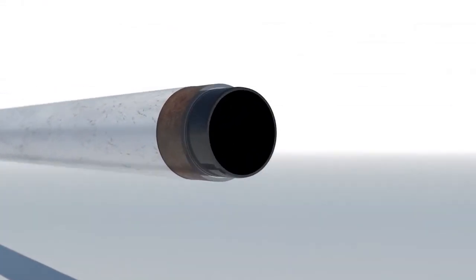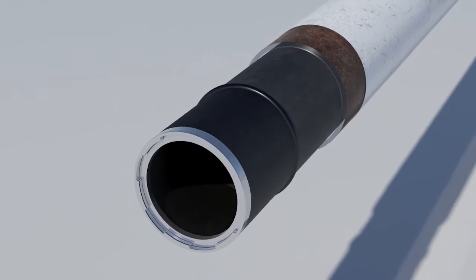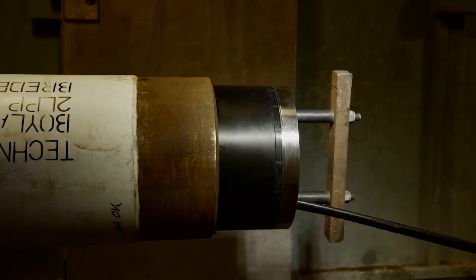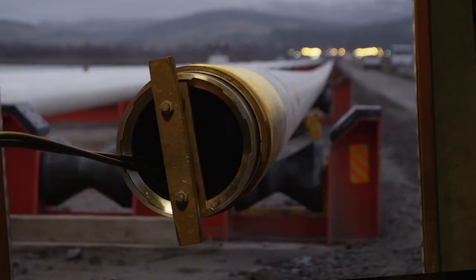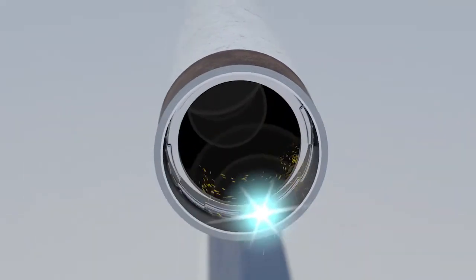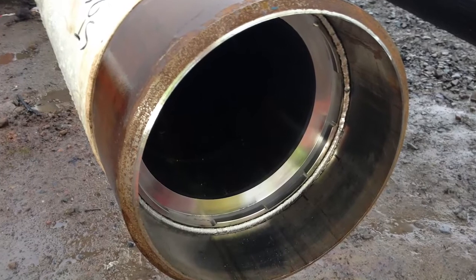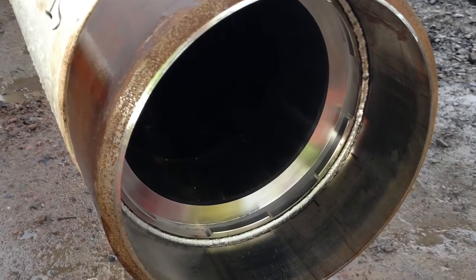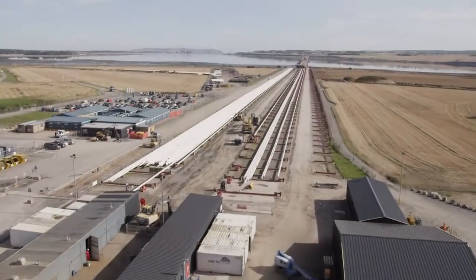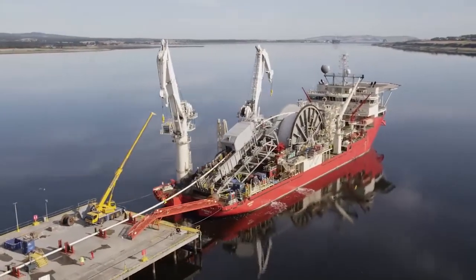The prefabricated hub is then fusion welded onto the liner end using the same process as for forming line joints, and beads removed. After cooling, the polymer liner is released and it then retracts into the pipe stalk. When the end termination reaches its designated position, a CRA fillet weld is made which secures it to the clad inner pipe surface. Any trapped air between the liner and the host is normally expelled as the liner relaxes, but additional conditioning may be carried out by hydrostatic charging before the completed stalks are connected together and spooled onto the delivery vessel for transportation and laying.